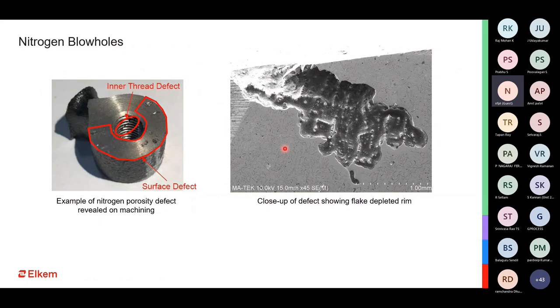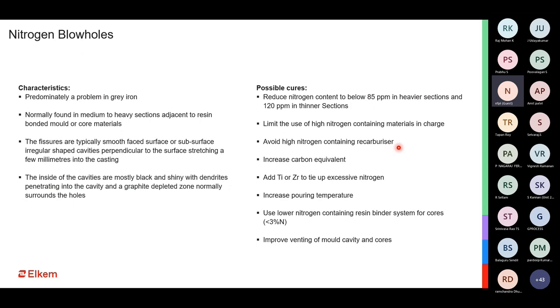The photograph on the right shows how the nitrogen fissure defect looks under a scanning electron microscope. It's taken at a much lower magnification, somewhere around 50x, and you can see how the region around it is also depleted of graphite flakes. So there is a rim of austenitic matrix which does not have any graphite flakes around it, and of course the surface and the shape of the defect will not be smooth. It will be more of a fissure than a blowhole.